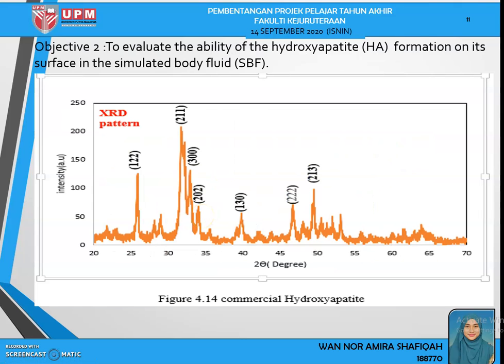So the second objective is to evaluate the ability of hydroxyapatite formation on its surface in the simulated body fluid. We tested the commercial hydroxyapatite using XRD. So this is the graph. The two theta values of hydroxyapatite are in a range of about 20 to 70. The peaks of this XRD are at 26, 32, and 46.6 degrees.